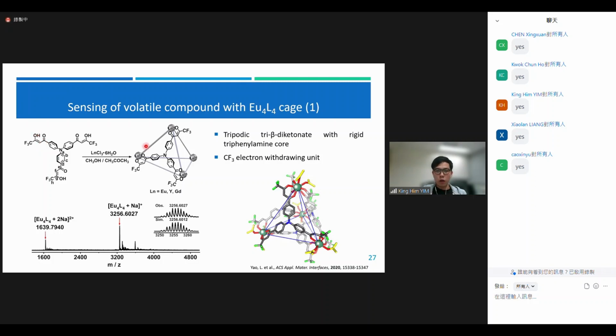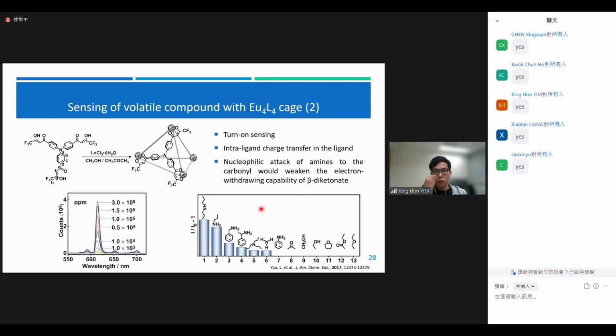So this triphenylamine cage's structure is confirmed by ESI-MS and also by X-ray crystallography. Here shows the X-ray crystal structure, confirming that this cage is a tetrahedron. They try to use this tetrahedron for sensing some of the volatile amine compounds. The sensing of this volatile amine exhibits a turn-on response, which can be attributed to the intra-ligand charge transfer in the ligand.